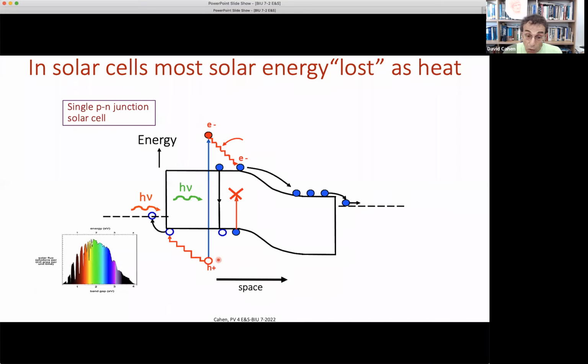Now, the photon will generally not be exactly the difference between the valence and the conduction band in terms of energy. It'll have more, or it has less. If it has less, too bad, we lose all the energy, it goes to heat. If it has more, what happens with the extra energy? Under all normal circumstances, we lose it because of thermalization. There's a very active field of research that tries to find ways to use it, so-called hot electrons.